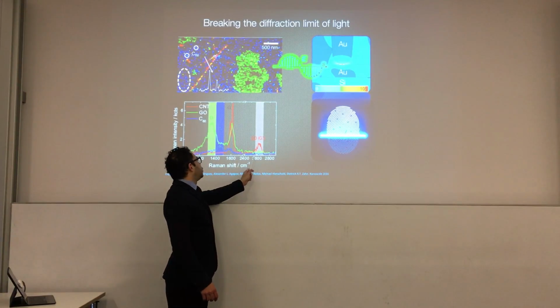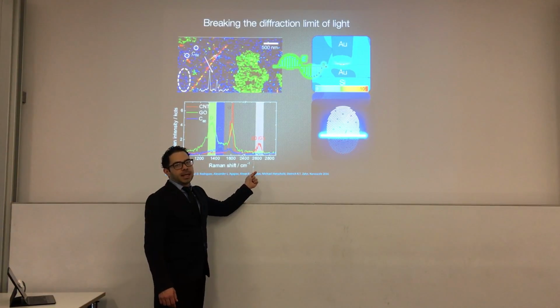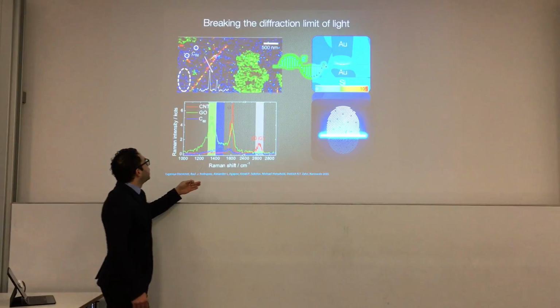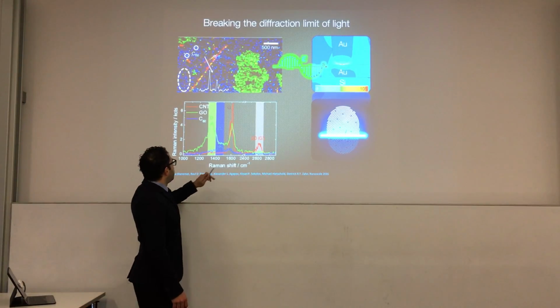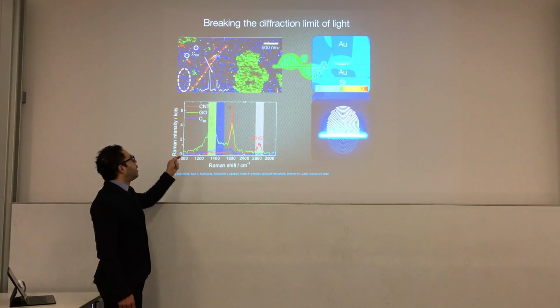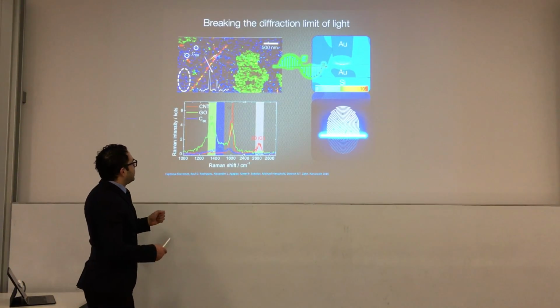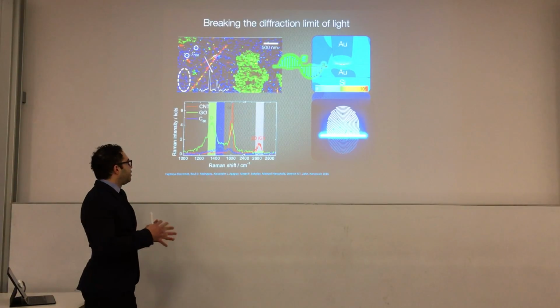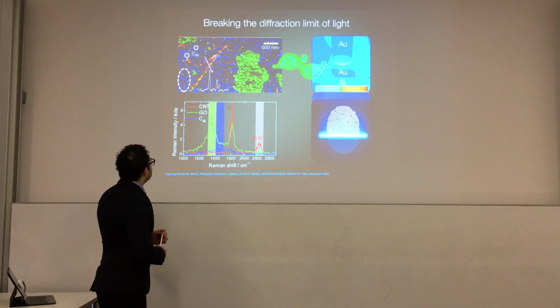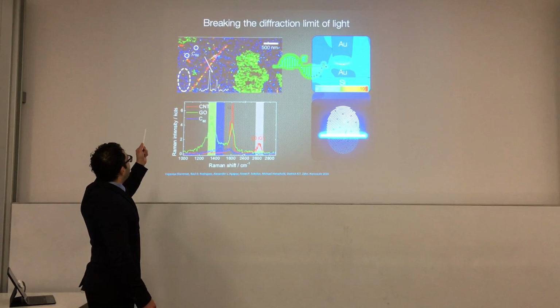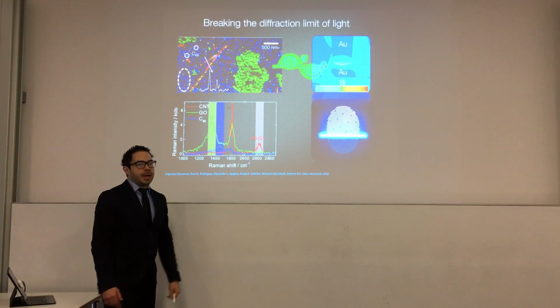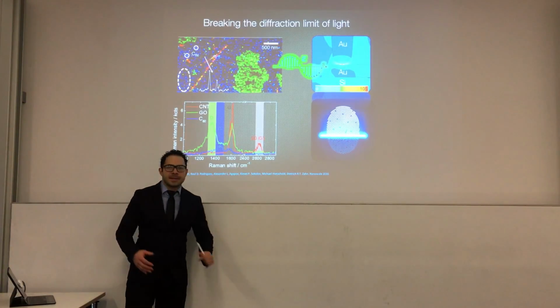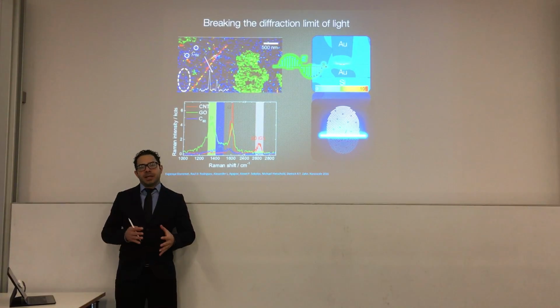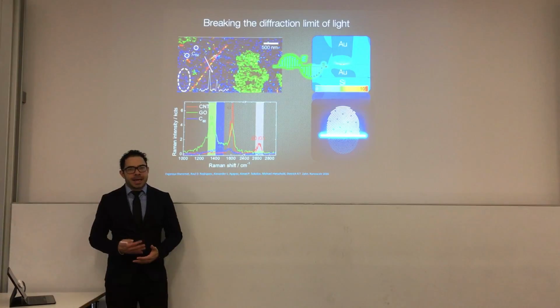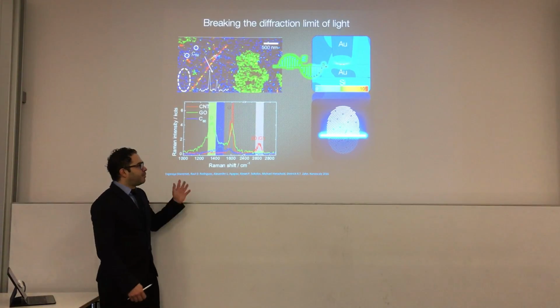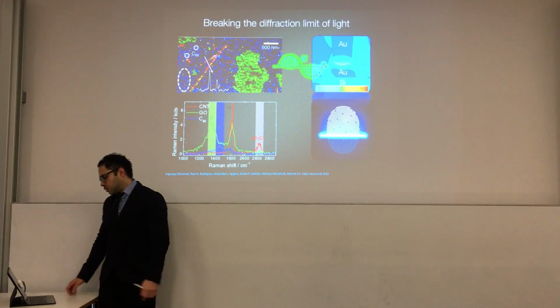So how we obtain that image is that I just take the intensity of this band, which is related to the 2D band of the carbon nanotubes, and I can see in red how the carbon nanotubes pop up. If I do the same with the D band of graphene oxide, you will see how clearly it illustrates where this graphene oxide is. And I do similarly with the fullerenes, and this C5 mode vibration of the fullerene makes it look like the small aggregates that you see, or the small aggregates that are everywhere around the surface. So this is the capability that coupling optics at the nanoscale with an atomic force microscope can give. You have the spatial localization, the amplification, and the chemical fingerprinting that optical spectroscopy gives. In this case, Raman spectroscopy.